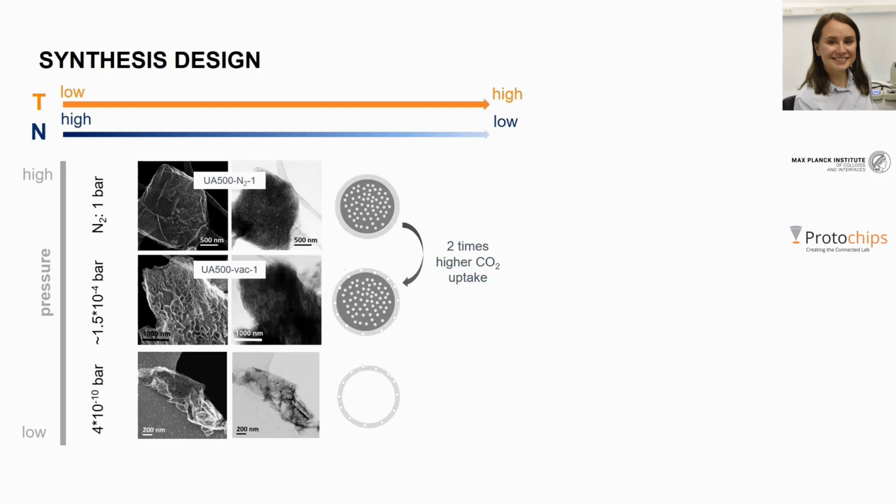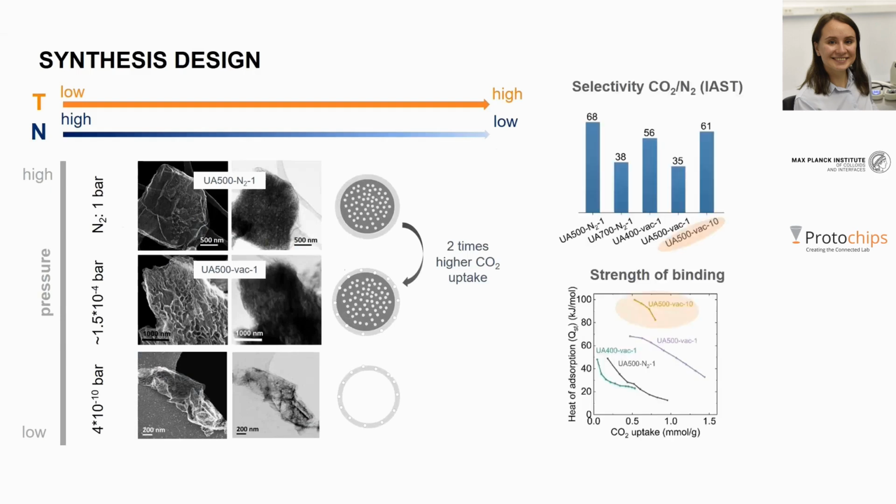So as a result, we were able to follow for the first time the condensation process of a molecular precursor at the nanoscale, and also we could show how one can control and tune the formation of pores in nitrogen-containing carbonaceous materials, which we realized by varying pressure and heating rate. Since these parameters change how the porosity of the surface develops and how further it affects the release of gases through the surface and bulk of the particles.